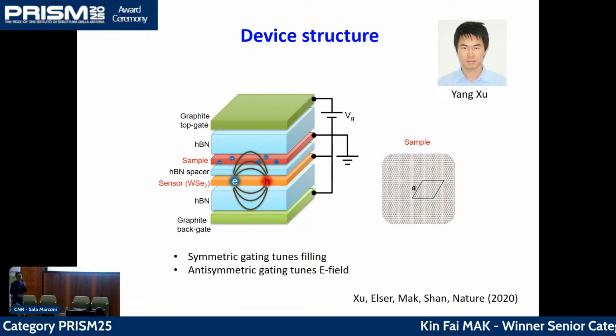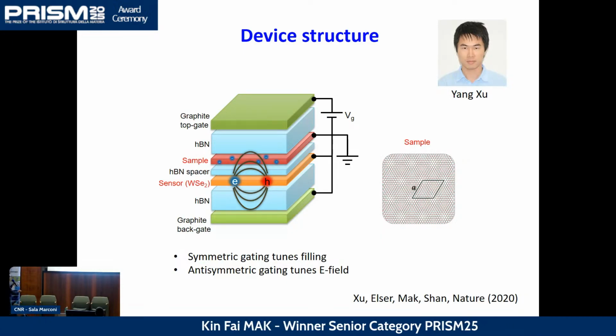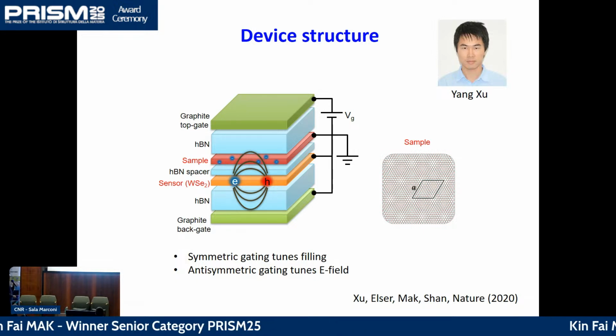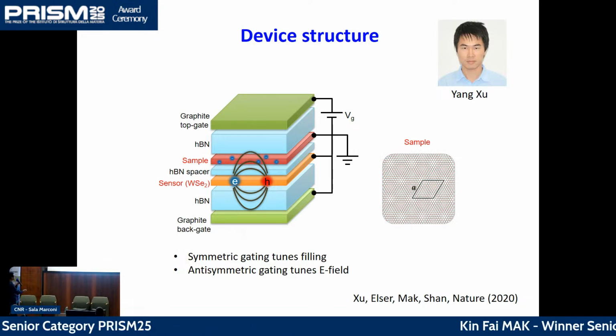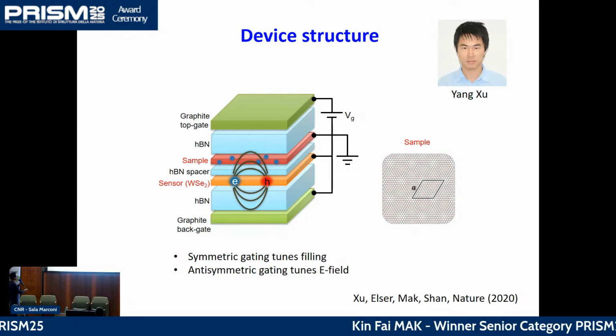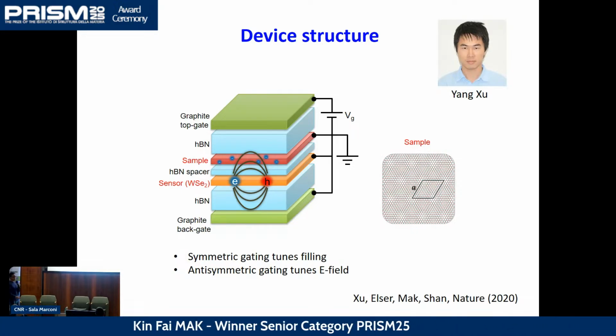And so with this idea, we built a device. The device is a little bit complicated. Again, this is a sample here, sandwiched by the gates. The gates allow us to tune the electron density in the sample. But very close to the sample, we put a sensor here in which we can excite this electron-hole pair.